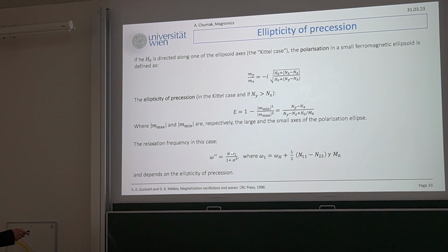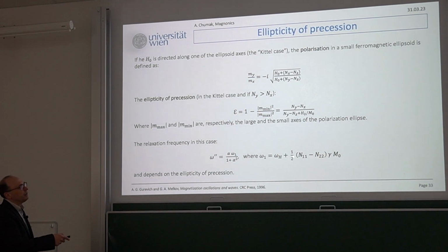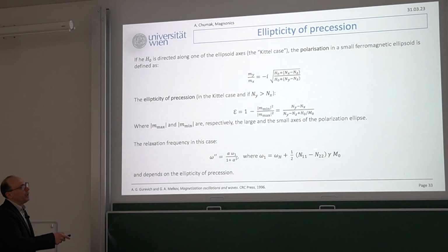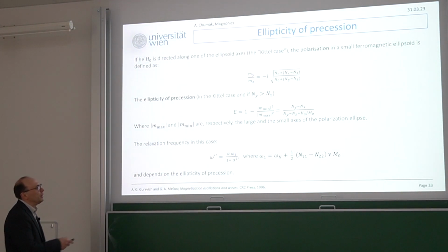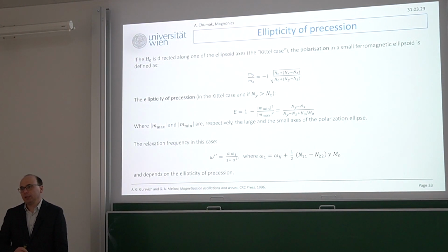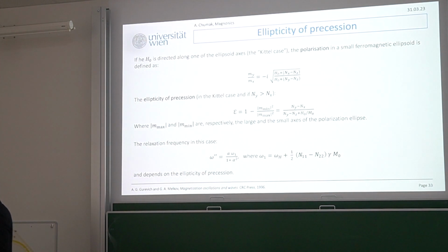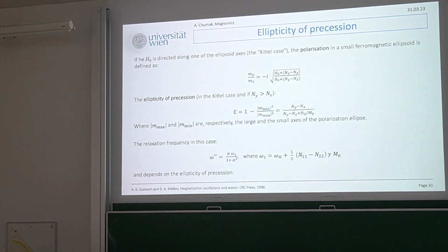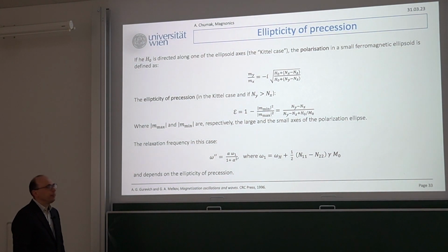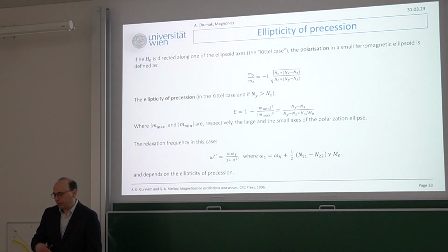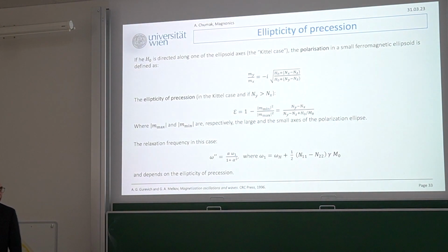Here it was simply the resonance frequency. And now this resonance frequency depends on N11, N22, like it's shown here. Therefore, we can conclude that lifetime depends on the ellipticity. We don't really take it into account in all cases. Pretty often this contribution is small and can be ignored, but in some cases it does matter. Therefore, keep in mind that ellipticity should be carefully considered if you want to get omega relaxation in order to define the lifetime of your magnets, for example.